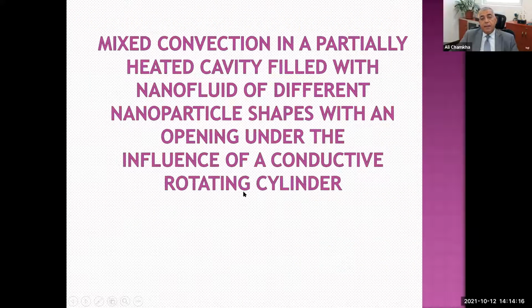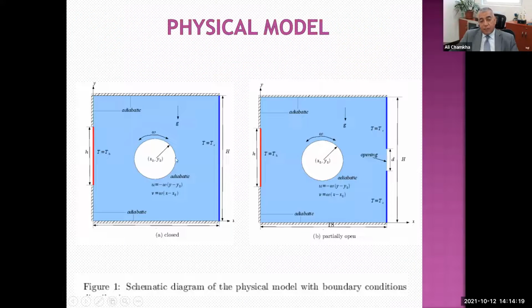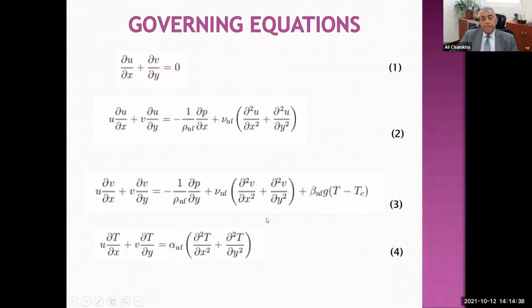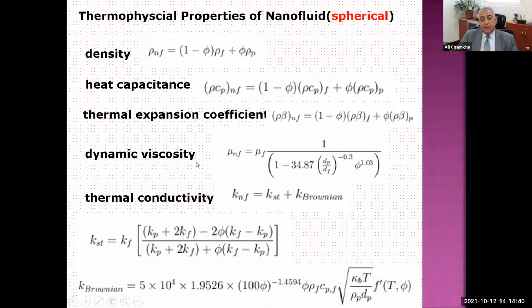Similar stuff. Now, I want to go to another problem where we have a closed cavity with a heated part, everything else here is a cooled surface, and it's insulated, and you have the cylinder rotating inside, and you have an opening. So we want to compare this system with opening and without opening. Similar type of equations. Here, the dynamic viscosity model we use is this. In the papers, you will find the reference for these models. And this is the thermal conductivity model we've used.